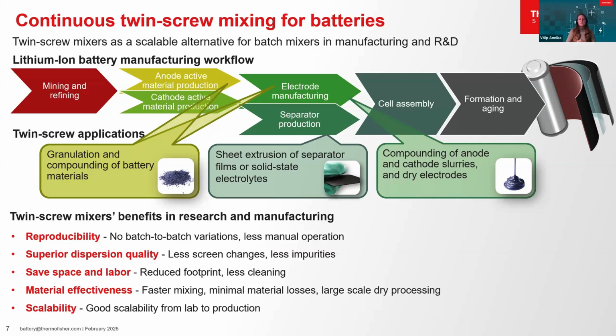In manufacturing, the twin screw mixers provide the following benefits over planetary mixers. The reproducibility is better. Twin screw mixers ensure there are no batch-to-batch variations, enhancing the consistency of the production process. There's less need for manual operation, reducing the impact of the individual operator handling. The higher shear forces in the twin screw mixers lead to superior dispersion quality. This results in fewer screen changes and less blockage of the downstream filters before the coater. The process also introduces fewer impurities, significantly reducing the presence of unwanted particles in the slurries. Twin screw mixers require less physical space, offering a reduced footprint. They also demand less cleaning and maintenance, saving both time and labor.